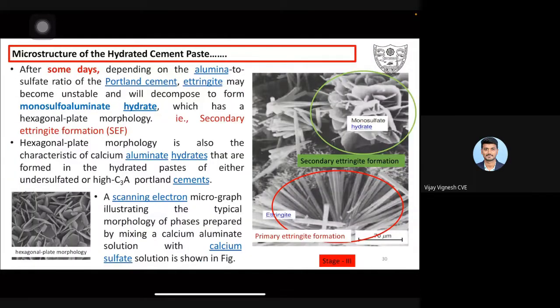Now after some days, for example 3 days, 4 days, depending upon the alumina to sulfate ratio in the Portland cement, ettringite may become unstable and will decompose to form monosulfoaluminate hydrates with the presence of alumina and sulfates. This ettringite may change from the needle phase to some other form, which is called secondary ettringite formation.